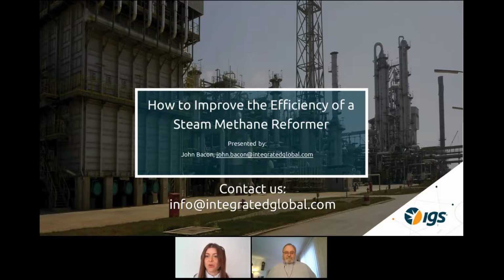Next question from Quasi. What is the life of this high emissivity refractory coating, and how often do we need to apply it? Well, you'll have seen in the case study there, the emissivity, or rather the flue gas temperature on the chart increased again after about 4 years. That's not typical. We generally recommend in the steam methane reformers that the coating is either touched up or reapplied after 6 to 8 years. 4 years is extreme, and it depends on the duty inside the unit, how hard the unit's being fired. But 6 to 8 years is a typical number for a steam methane reformer.